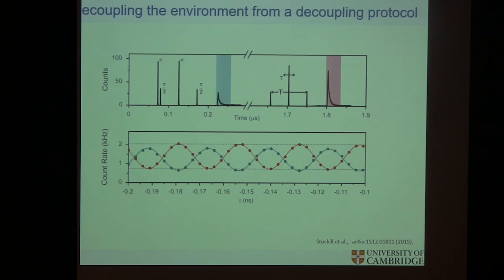And the way we do it is, poor man's version, the simplest thing you can imagine. You do your whole operation alternating with a 0 or a pi flip before and after. So you keep trying to polarize nuclear spins one way in one shot, and then the other way in the other shot, this way, other shot. So you never build up nuclear spin polarization. That's our trick. So all the experiments I'll show will have this in the background, that there's an alternating sequence.